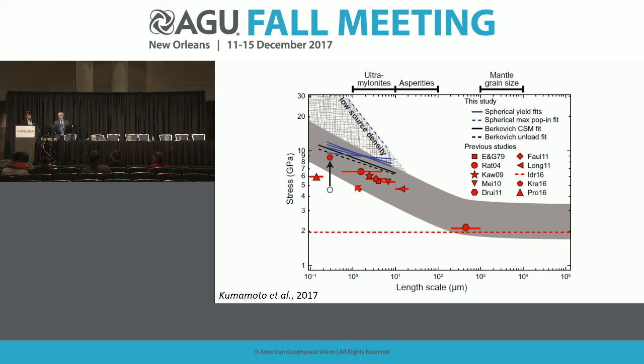And one of the neat things about this is there's this study by Idrissi that actually looked at the mobility of a single dislocation in a kind of a neat technique. And what's neat about that is that at really coarse grain sizes, what you're seeing almost matches this single dislocation mobility. Now, one of the things that makes these types of data really complicated is if you try to deform these things to higher strain, they get stronger than the bejesus. They work harden, so the yield stress is really the thing that scales really well with grain size.